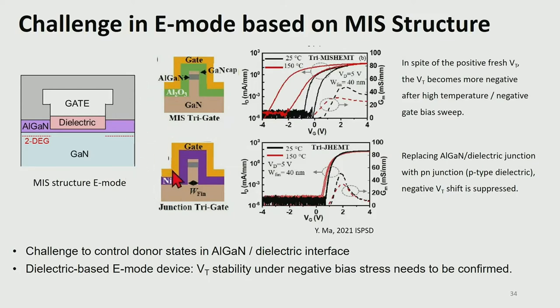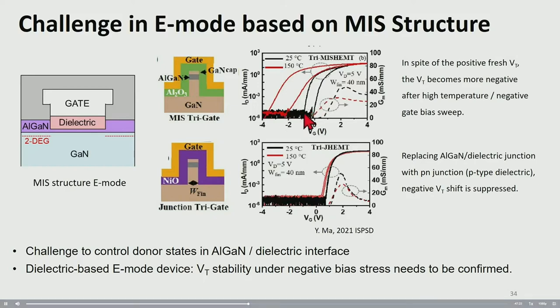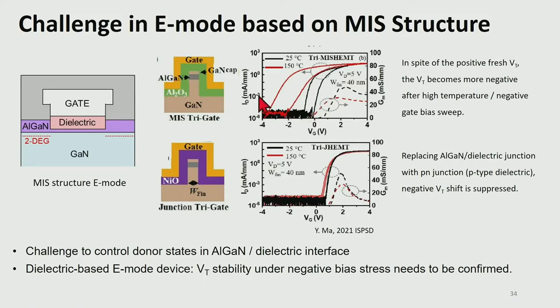So in this study, tri-gate GaN devices were fabricated with two different gate structures. In the first device, aluminum oxide was used as a gate oxide. So the gate structure is like a typical MIS structure. In this device, especially at room temperature, the VT is quite positive thanks to this tri-gate structure. Although there is some hysteresis, VT is close to zero, so you can effectively call it an enhancement mode device. But if you go to the higher temperature and do the forward and reverse bias sweep, you can clearly see that there is a large negative VT shift. So even though at time zero it can be called an enhancement mode device, after the stress it becomes a depletion mode device.